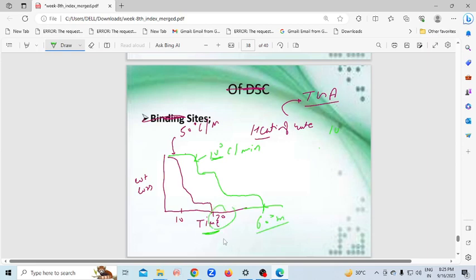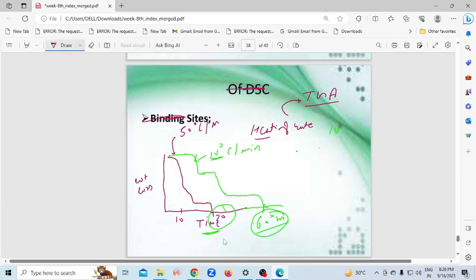Initially it takes only 20 minutes at high heating rate, but at lower heating rate, when temperature increases, it takes more time to decompose. So this is all about how heating rate will change the time of decomposition, and how your thermograph also will be changed. Then we can discuss the same thing by plotting with temperature also. Here we plotted with time. Now I am going to plot weight loss with temperature.